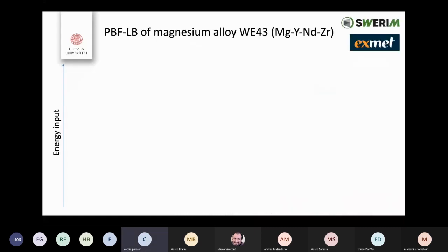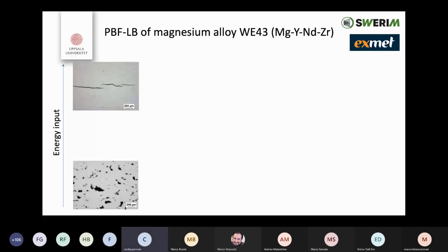So what we have done is try to print then a magnesium alloy that is commercially available in these types of screws that I showed before. And what we've seen is, of course, if you have too low energy, you get a lot of unmelted material and pores. If you have too high, you get an excessive evaporation of magnesium and cracks in the material. And you need to find this optimum energy input to be able to get a non-porous material.